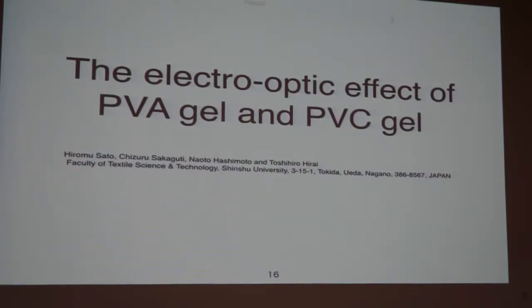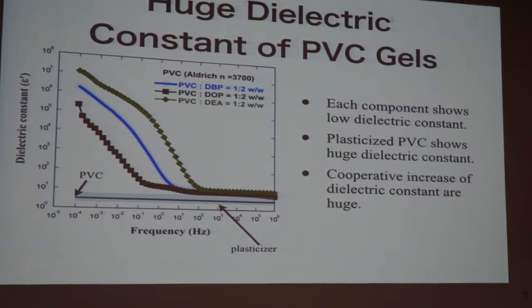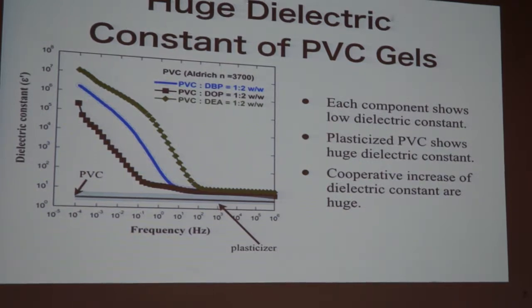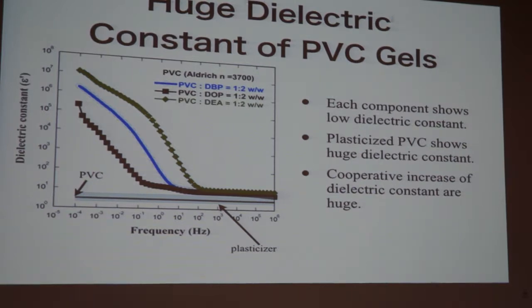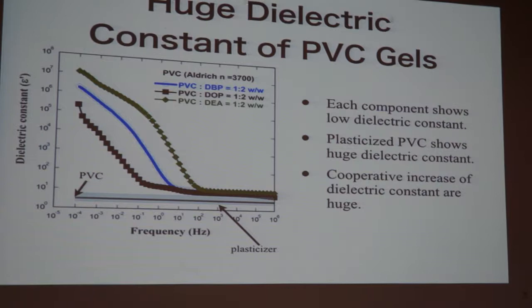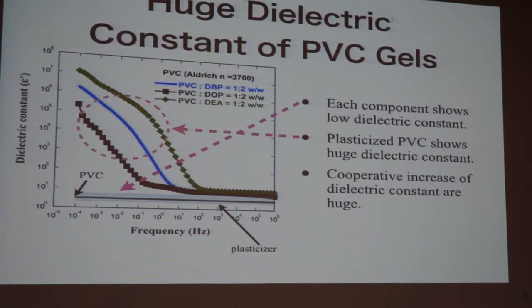But this experiment, and this is the result. When we add the plasticizer, all of them show a huge increase of the dielectric constant in the low frequency range, not the high frequency range. So when we allow the very slow reaction, then this will be enough. Each component shows a low one, but the plasticized PVC shows a huge dielectric constant.